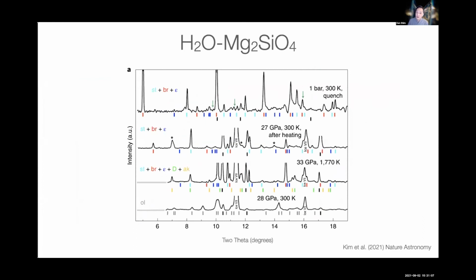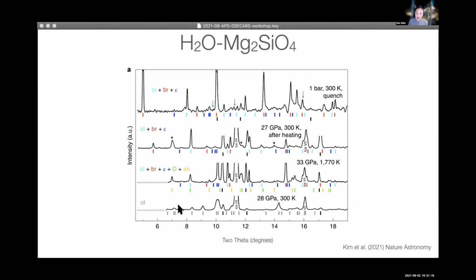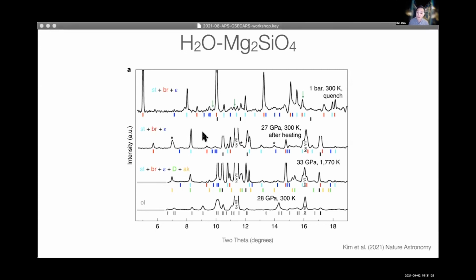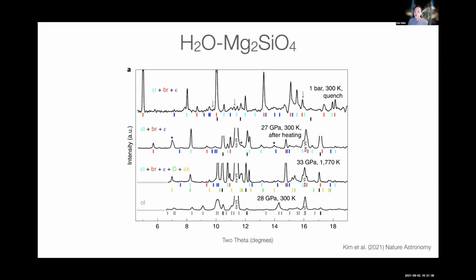We also studied olivine in water. So these are water-saturated conditions. Then we conducted laser heating. We found that when we start with olivine, high temperature diffraction patterns start to show very silicon-rich minerals and very little Mg-rich minerals. That was pretty puzzling. And then when we decompress from high pressure to 1 bar, we see sudden sedimentation of Mg(OH)2, brucite. That was pretty surprising.